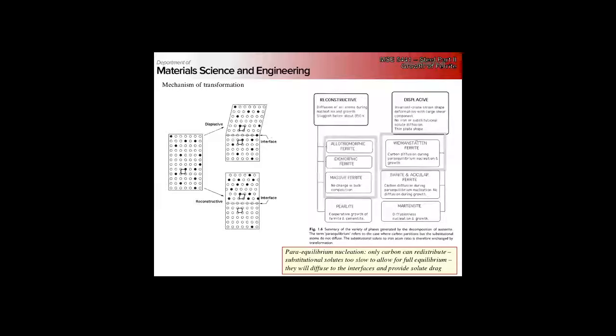We also introduced this notion of para-equilibrium nucleation, which says these things are happening at a time scale such that carbon can easily diffuse, being an interstitial, but for substitutional elements, they just physically don't have the time to diffuse. So we're not at a true thermodynamic equilibrium, we're at a para-equilibrium state.